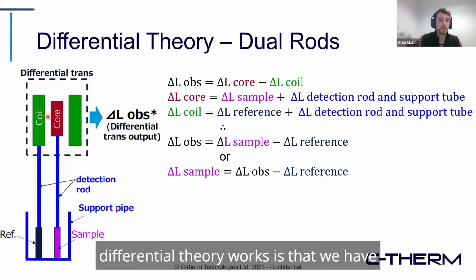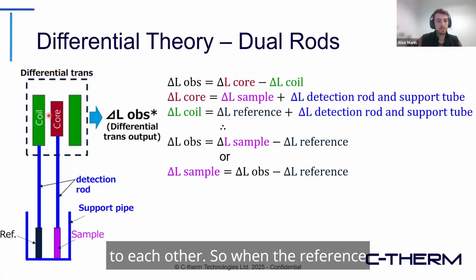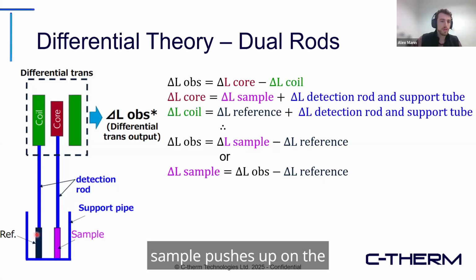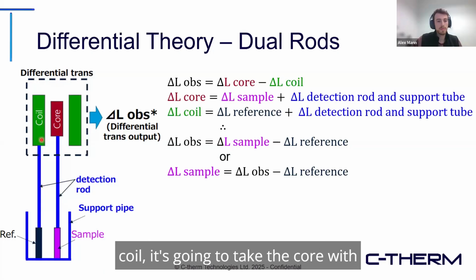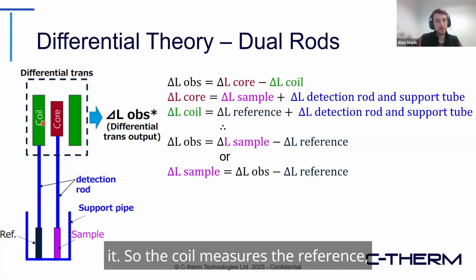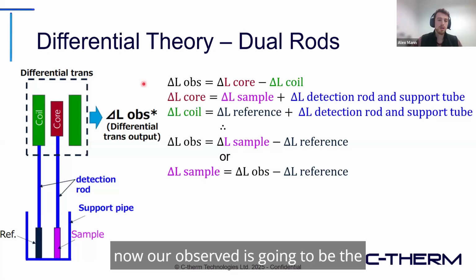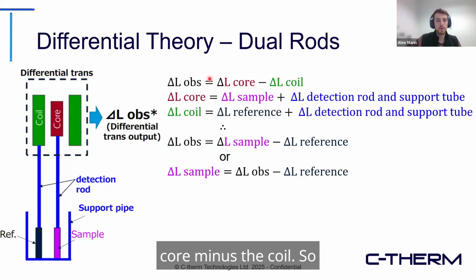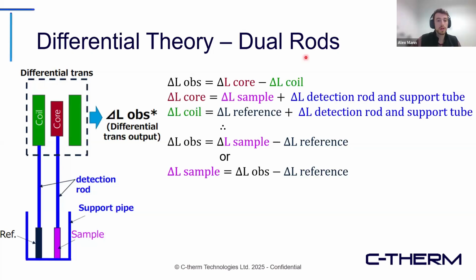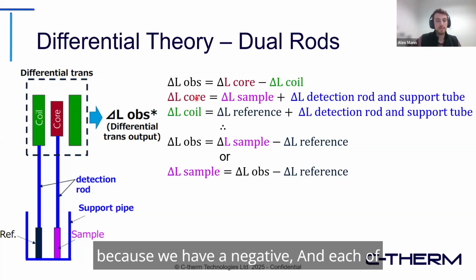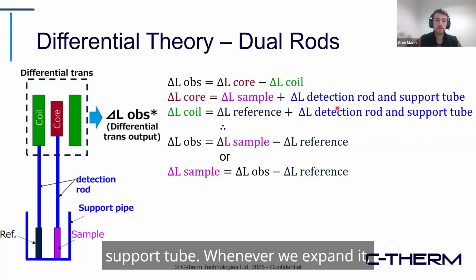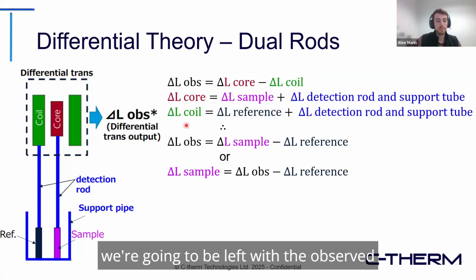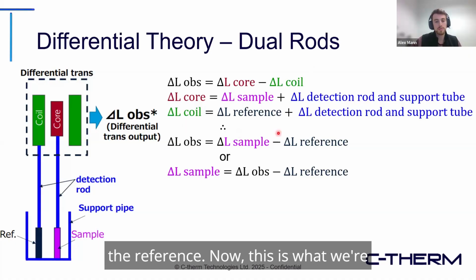The way differential theory works is that we have the coil and the core connected to each other. When the reference sample pushes up on the coil, it takes the core with it. So the coil measures the reference, and the core measures the sample. Our observed is going to be the core minus the coil. Because we have a negative, and each of these terms includes the detection rod and support tube, when we expand it, we're left with the observed expansion being the sample minus the reference.